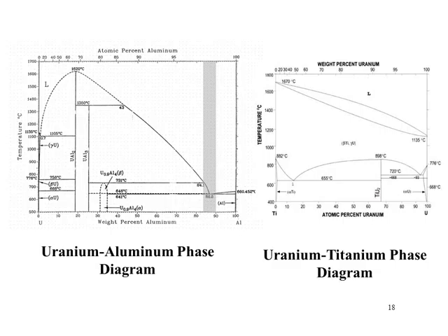Here are an example of two phase diagrams. We see the uranium and aluminum phase diagram. This is the liquidus phase. Here's uranium, here's aluminum, here's 100% uranium. And these are the different phases. So if we start having mixtures, we'll form two phases here, one being the uranium metal, and one being this intermetallic, uranium aluminum 2.